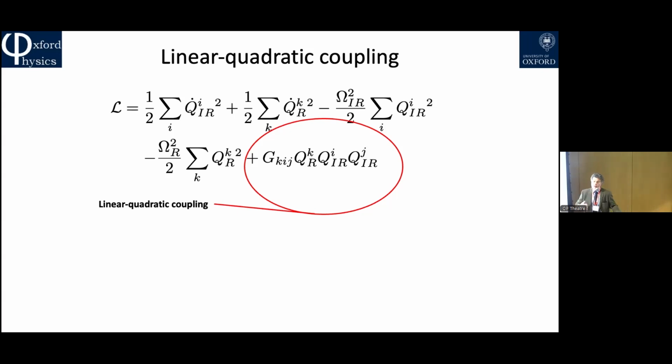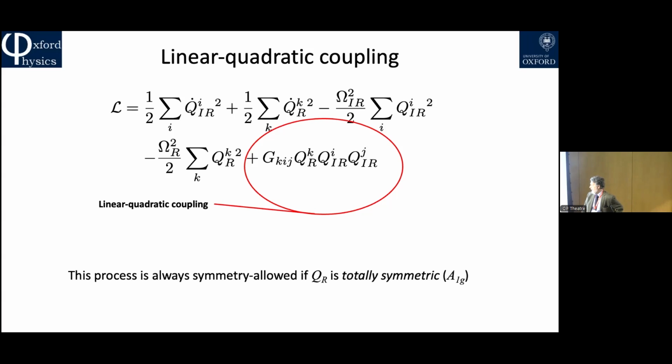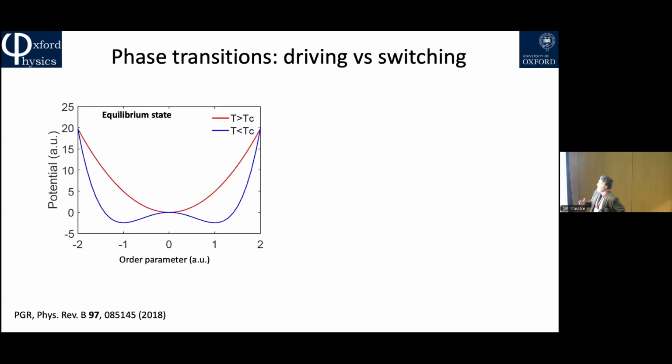This gives rise to a totally symmetric perturbation, which is rectified in the material, which is a sort of weird pressure, if you want, weird hydrostatic pressure. So if you apply pressure to a material, unless you go through a phase transition, you don't change the symmetry. And this is a sort of weird pressure. Right? You change the atomic coordinates in a different way with respect to pressure, but it's totally symmetric. Now, what is the effect?